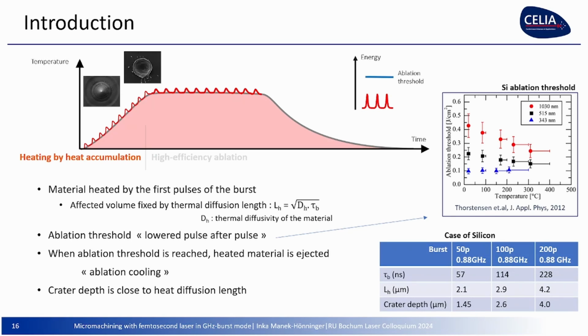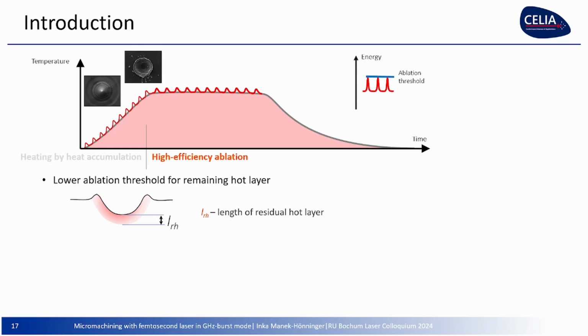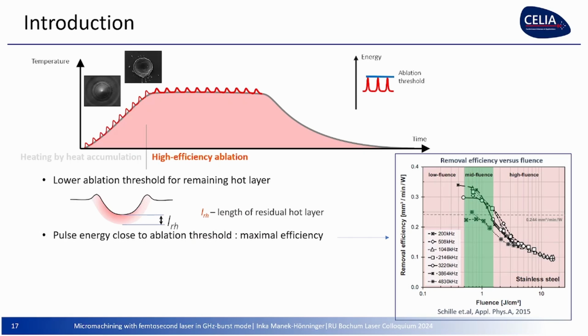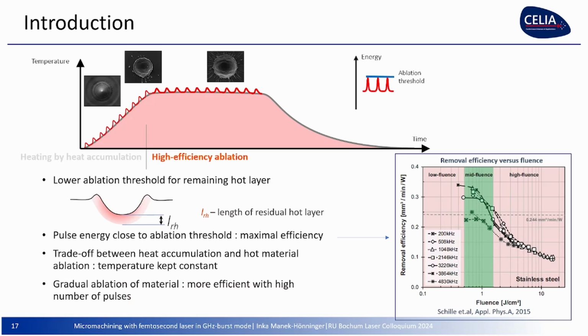Okay? But still, there is some layer or volume of the material that is preheated. There's still something remaining, and then we are closer to the ablation threshold, and then we reach it. By the way, the pulse energy needed is then very close, so that's where you're most efficient. Each individual pulse of the burst that follows needs just a little bit, and all these pulses can contribute to ablation. That is what makes it efficient. That means the first pulses of the burst don't contribute to ablation, and the following pulses, after you've reached the ablation threshold, contribute to ablation.